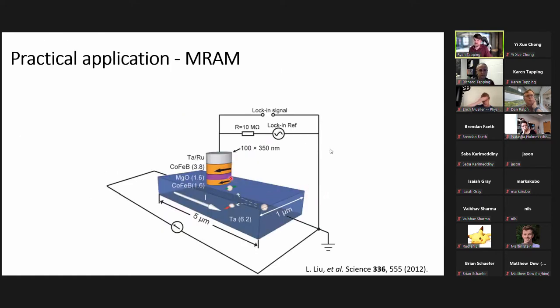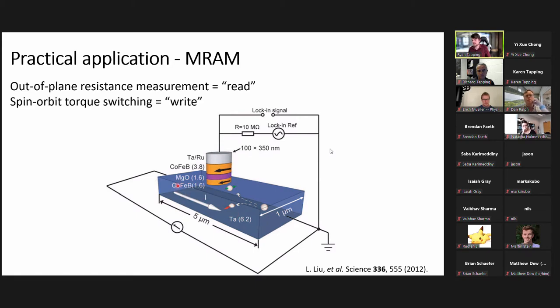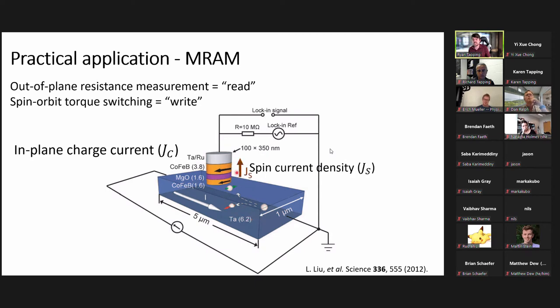One practical application is magnetic RAM or MRAM. The idea is that you can read or write states using a magnetic tunnel junction with two magnetic layers. Due to tunneling magnetoresistance, we can measure the relative orientation of those magnetizations through an out-of-plane resistance measurement. The key idea is using spin-orbit torque switching to write: a charge current flows in-plane and then spin current density flows out of plane, imparting angular momentum on the free magnetic layer and causing switching.